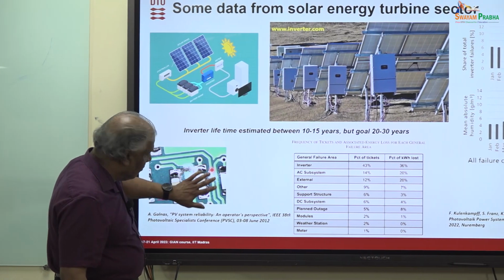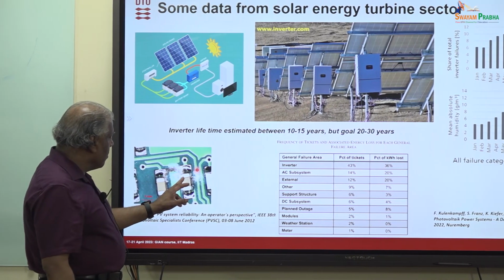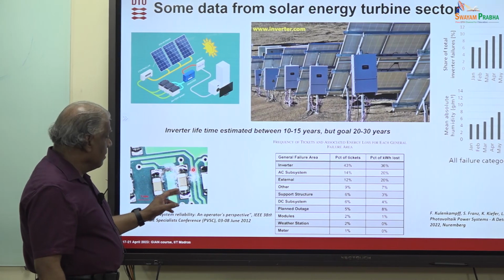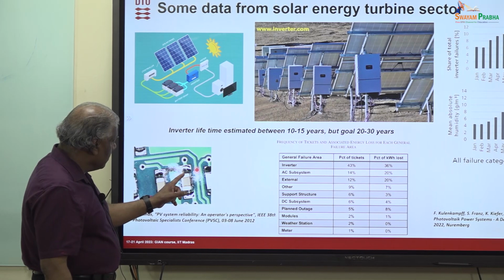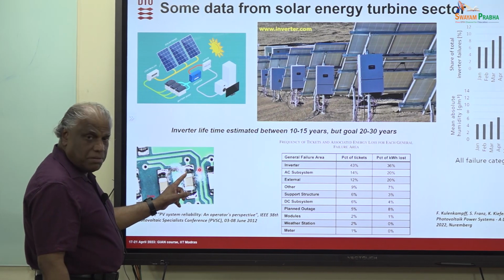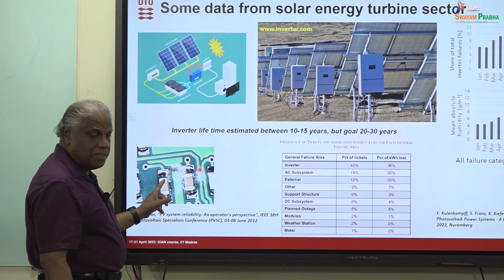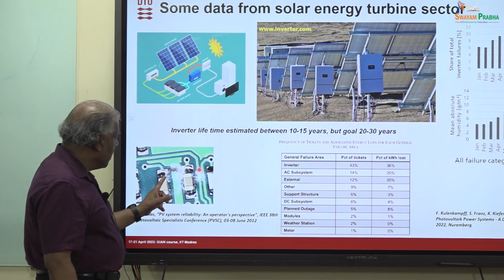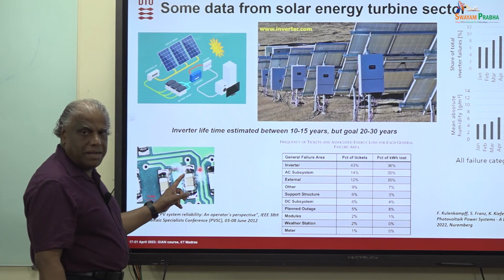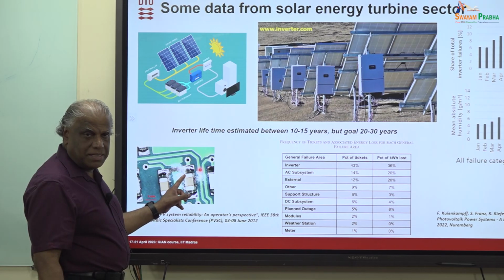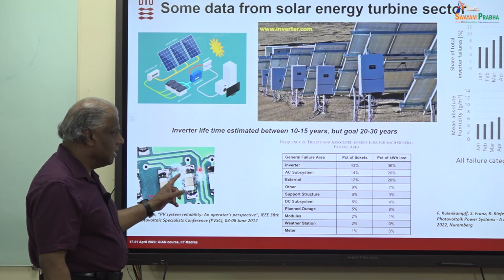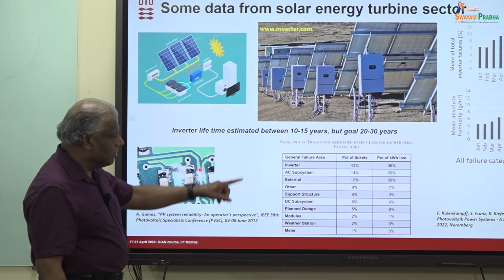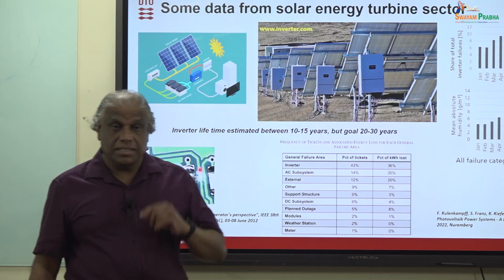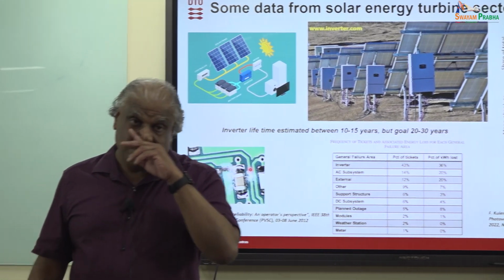So there was a water film. These two components got connected, and maybe this was the positive terminal and this was the negative terminal. So the metal has dissolved and deposited between these two and made an electric short in this particular case. I'll come to the mechanism of this one later, and that's what has happened. So that's what you see in that case. So there's a real correlation. That's the reason that everybody is worried about humidity related failure.